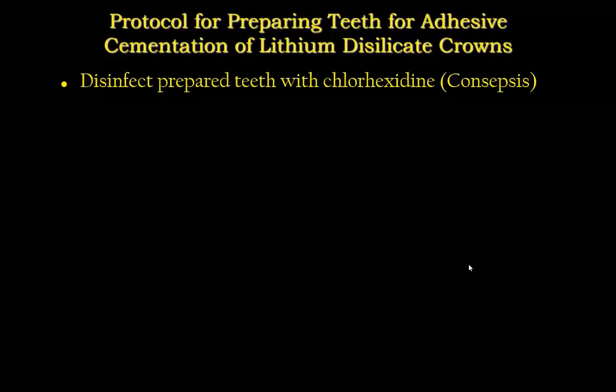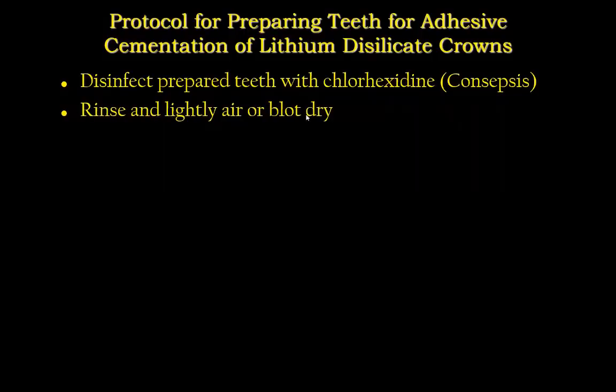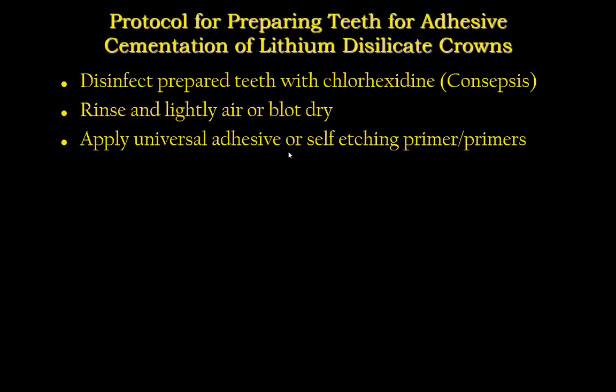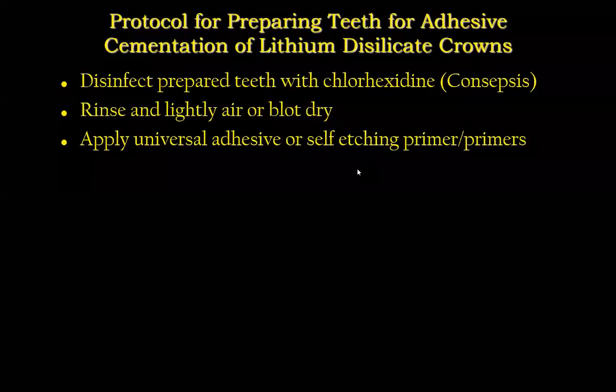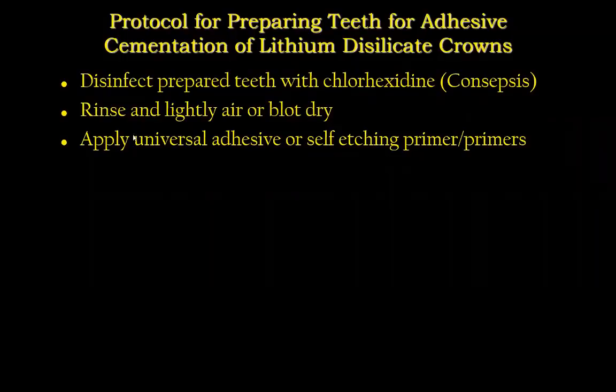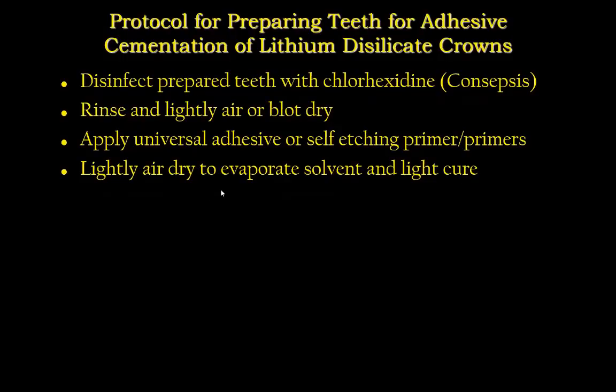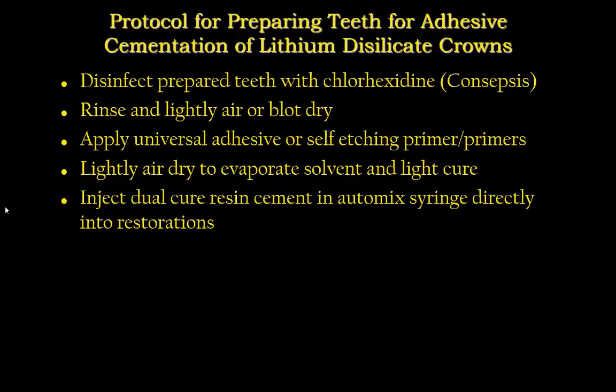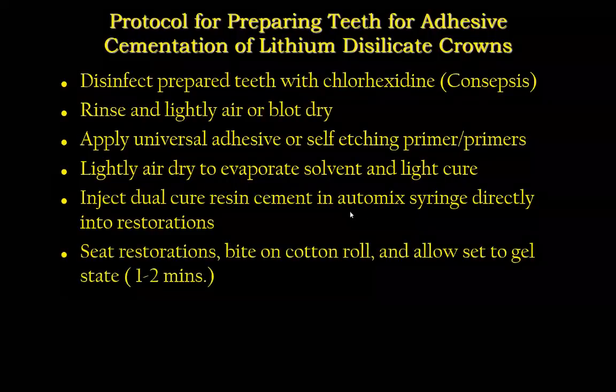So how do we prepare the teeth? Well, we're going to clean with chlorhexidine. We're going to blot dry, okay? And I'm going to put cotton rolls in because I'm using a self-etch technique here. If I'm bonding for a full crown where there's little or no enamel, I'm going to put my universal adhesive on, lightly air dry, evaporate the solvent. I'm going to inject. While I'm doing that, my assistant is taking the crown. She rinses it, she dries it out, and she takes a dual barrel syringe, whatever cement she's using, and injects it right into the restoration.